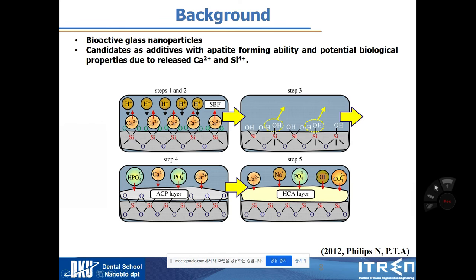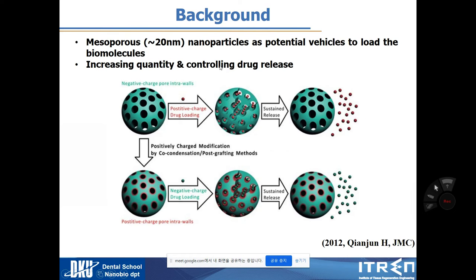So I want to focus on bioactive glass nanoparticles. What is it? They have apatite-forming ability and biological potential due to the release of calcium and silicate ions, which means we can regenerate dentin tissue when we apply this bioactive glass. This bioactive glass also has mesopores, meaning 20 nanometer pores like this, and they can load some biomolecules. When biomolecules are loaded in these small 20 nanometer pores, we can control drug release efficiently, which means we can successfully load and deliver our drug of interest to the target site.